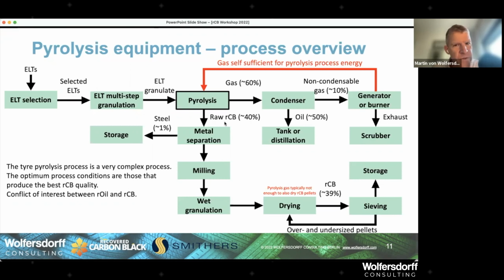What you would need to do is separate the metal. In granulate, there can be up to 1% metal still in. If you put in whole tires, of course, you have much more metal than that. And the metal you would store and resell. Clearly the metal after pyrolysis is not as valuable as if you separate the metal mechanically before the pyrolysis. So the price of the recycled steel after pyrolysis, after the heat treatment, is not as high as the steel price which is mechanically separated.